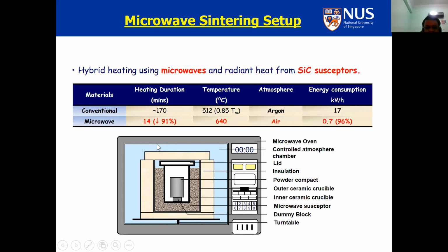We pre-calibrated the microwave. We switch it on, say for 14 minutes, it reaches a temperature of 640 degrees centigrade, and we switch it off. That's all we have to do, switch on, switch off. So we are able to sinter in 14 minutes when the conventional technique takes 170 minutes. That is a saving of 91% in the heating duration.